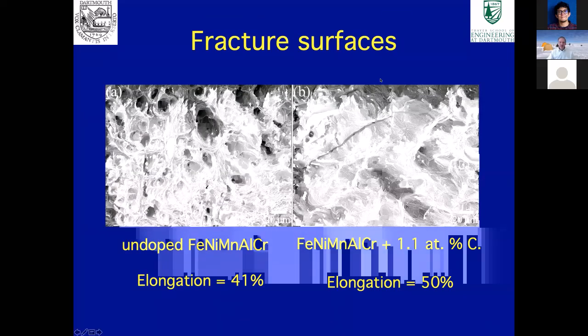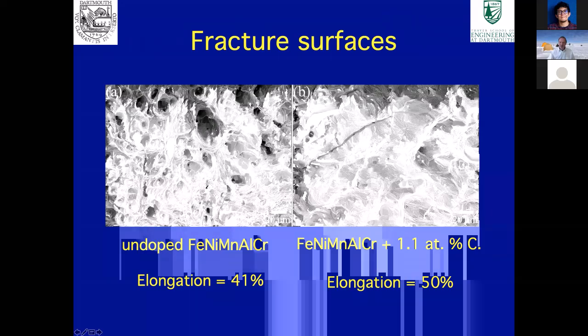The other interesting thing is the change in fracture when you add carbon. So this is the undoped material. You see a typical dimple ductile type rupture. When you add carbon, you get more ductility, but you lose that. It looks more like a glassy fracture on the surface.